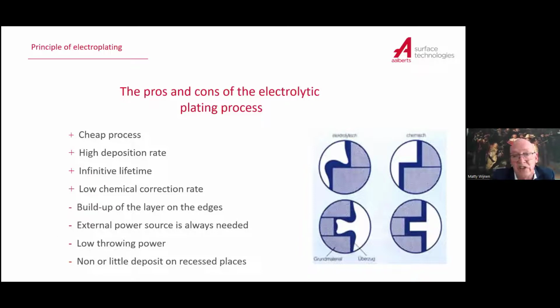Disadvantages, and that's what you see on the right side. You see the first two pictures, the layer buildup in the dark colors is on the edges more, and in the deep recessed places less. And if you compare that, for instance, with the chemical nickel process, which is on the side, you see that is not the case. So you have buildup of the layer on the edges. You have an external power source. You always need a rectifier. You have low throwing power and none or little deposit on the recessed places.